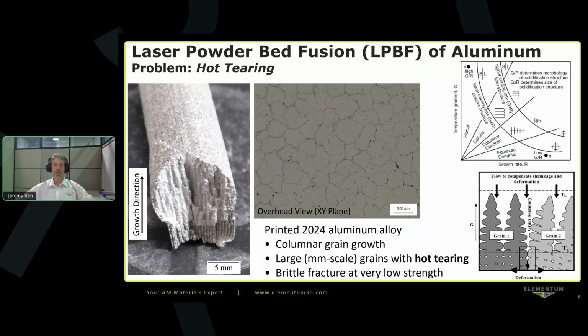This is very common where you take an alloy that was designed for wrought processing, like most high strength wrought aluminum alloys, for example. If you just try and take that same composition and print it with a powder bed fusion process or other fusion process, you tend to get this type of microstructure, and you have problems with cracking, and it's functionally unusable. In this example, this is a printed 2024 aluminum alloy. And because of this, you would get very brittle fracture at low strength, essentially unusable. You might be able to make something that looks like a part, but just don't apply any stress to it.